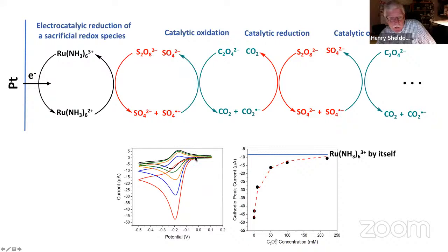What happens is you start, I got too many curves here. You start with the reversible response for ruthenium hexamine. You add the persulfate, the current gets really large. And then you keep adding more and more oxalate, and the current decreases, and it goes right back to the original ruthenium hexamine reduction CV. All right, the curve when you just have ruthenium, and the curve when you got oxalate and persulfate and a lot of oxalate, those two curves are very, very similar to each other.